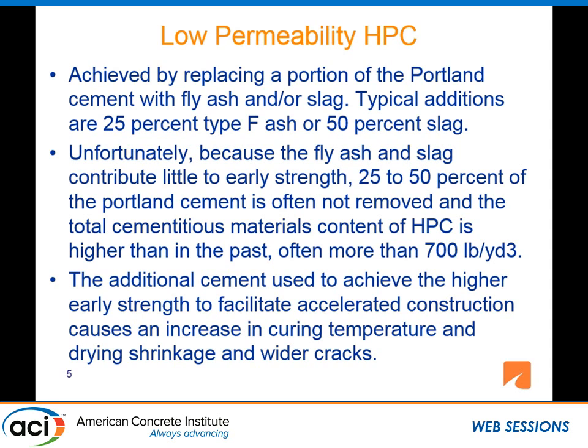Unfortunately, because the fly ash and slag contribute very little to early strength, 25 to 50% of the Portland cement is often not removed. And the total cementitious material content of these high-performance concretes is higher than in the past, often more than 700 pounds per cubic yard. The additional cement used to achieve the higher early strength to facilitate accelerated construction causes an increase in curing temperatures, drying shrinkage, and wider cracks.